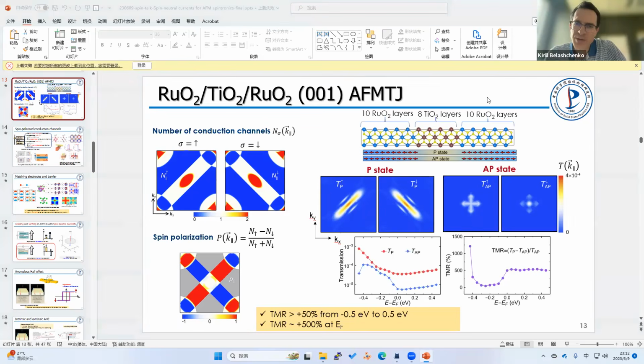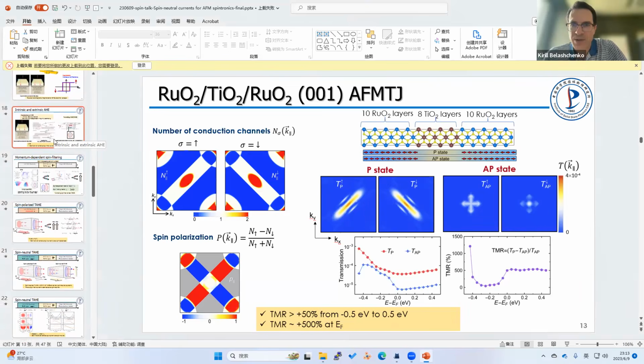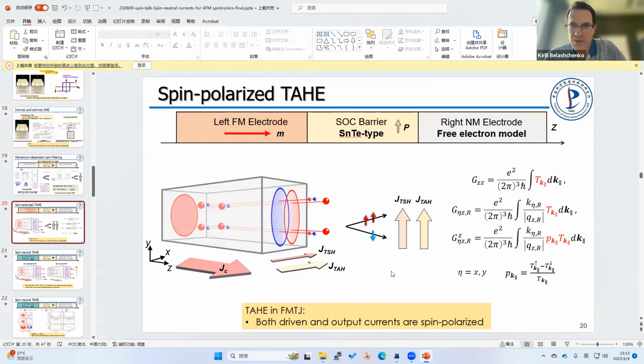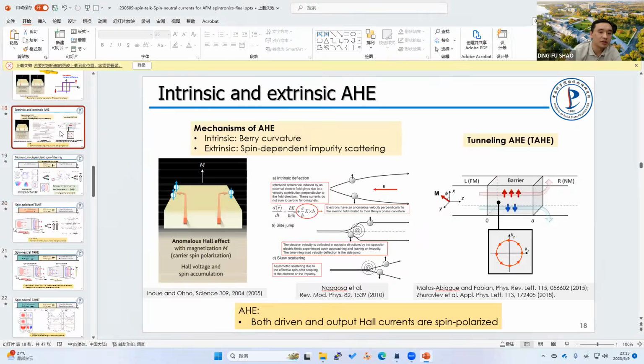So you discussed the relation of the anomalous Hall effect and the spin Hall effect in some contexts, in terms of the anomalous current being spin polarized and generating the spin Hall effect. But I don't think there's a direct relation between those, right? The spin current is not just the spin polarization times the charge current. I think this was discussed in the context of the spin anomalous Hall effect in the ferromagnets by Vivek Amin and Mark Stiles in their papers. So if you have those effects allowed by symmetry, you can have both currents, but they're not simply proportional through the spin polarization. Is it the same situation here with the tunneling effects?